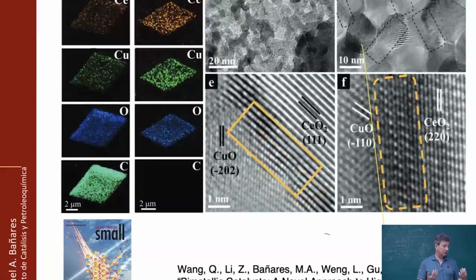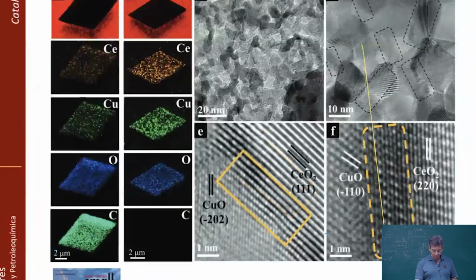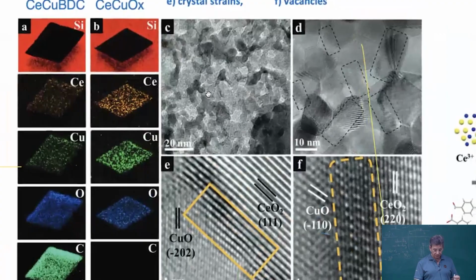That makes sense, because you are making a porous oxide out of a metal organic framework component. And the way it looks is like that. You see a big amount of crystallites. If you look more into detail, you see different kinds of domains. Some of them correspond to ceria, some correspond to copper, and then you get these mismatches between the lattices, which ultimately foster the creation of defective cerium sites at the interface between cerium and copper.